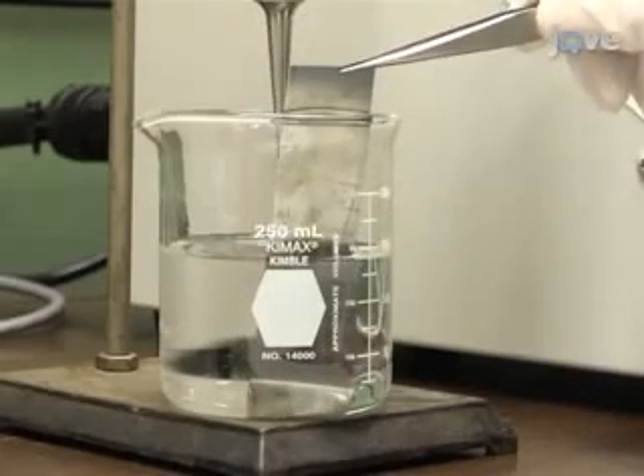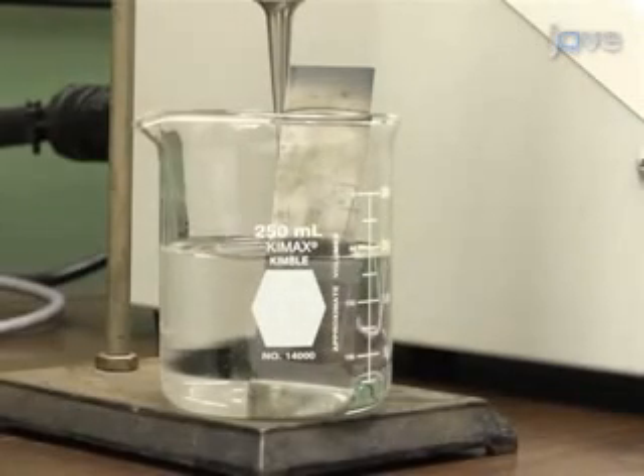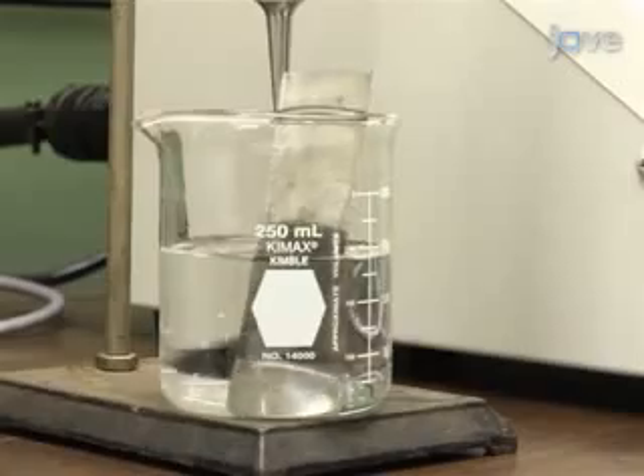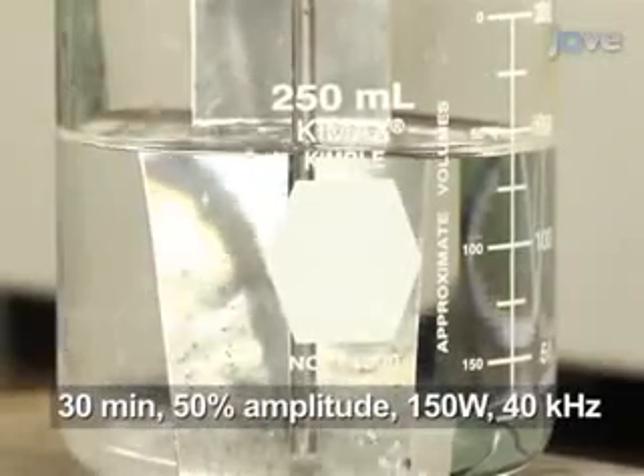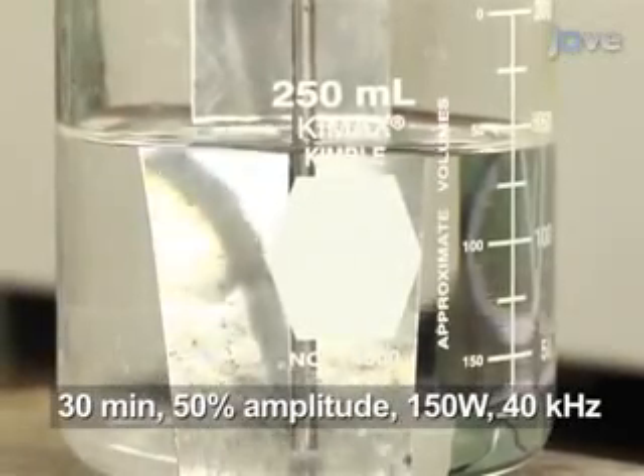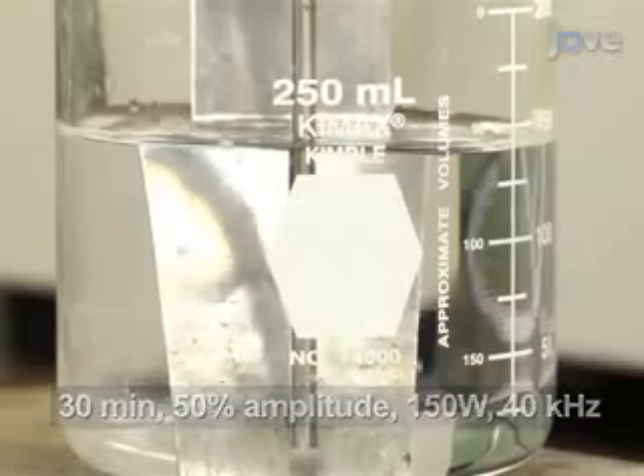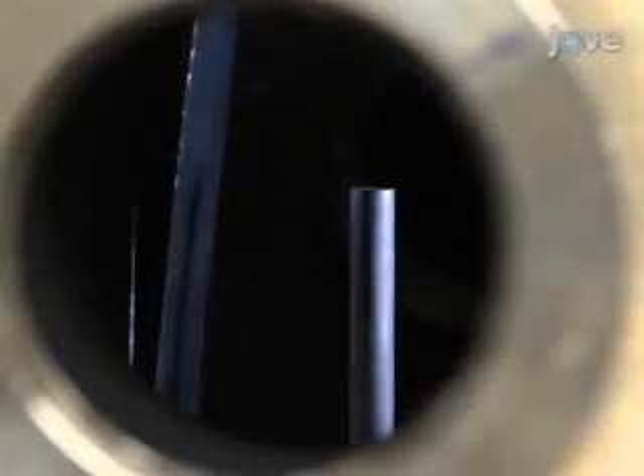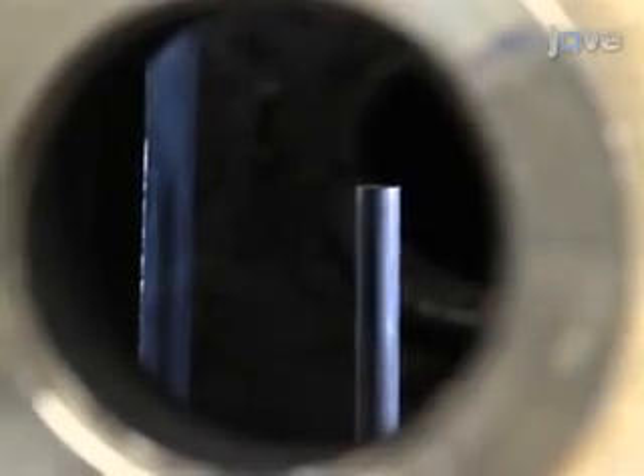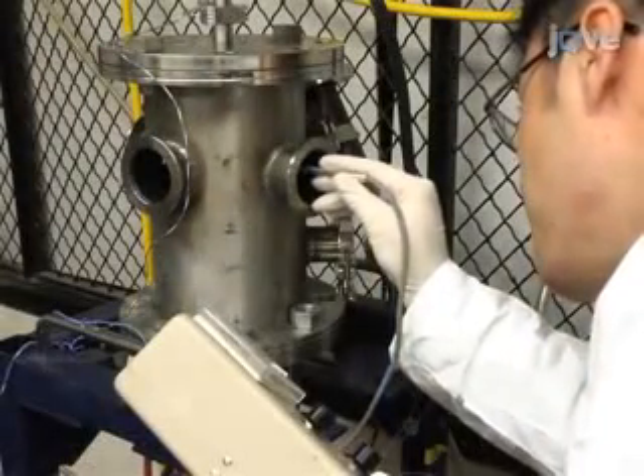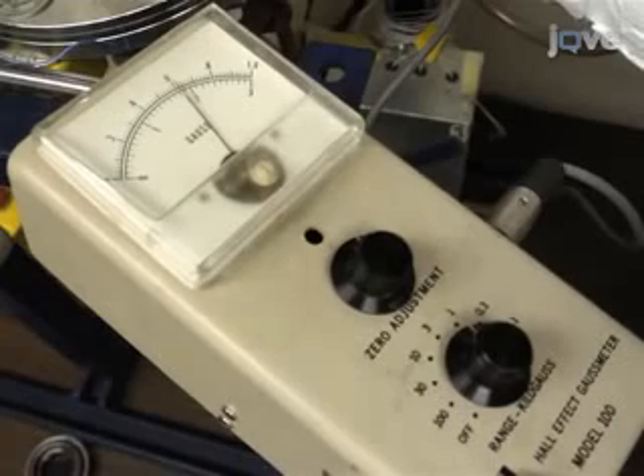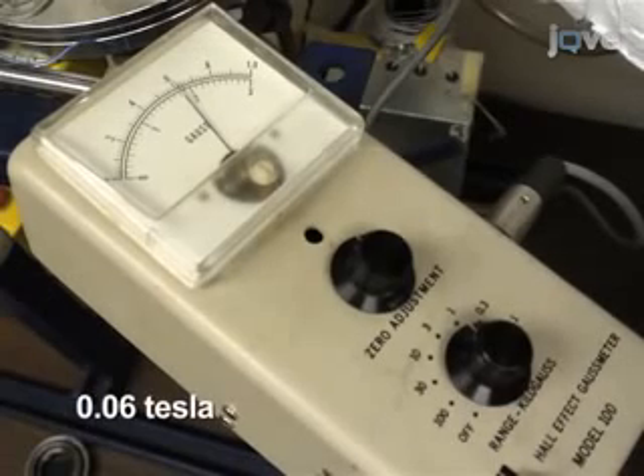Using an ultrasonic dismembrator with acetone and ethanol, remove the surface contamination for 30 minutes with a 50% sonicating amplitude, 150 watt output power, and 40 kHz frequency. Attach the molybdenum sheet to one side of the permanent magnet and turn this side towards the electrodes. Using a Gauss meter, measure the magnetic field in the interelectrode gap. Keep the average magnetic field between the electrodes at about 0.06 Tesla.